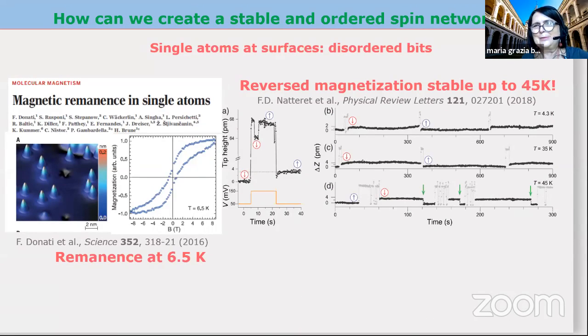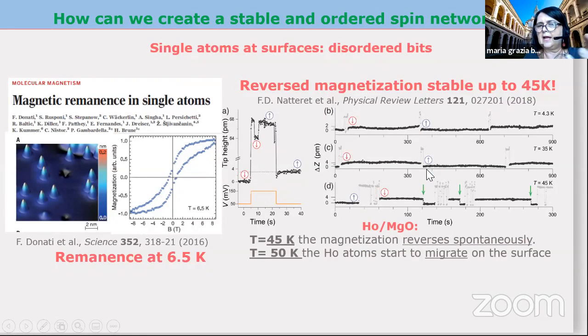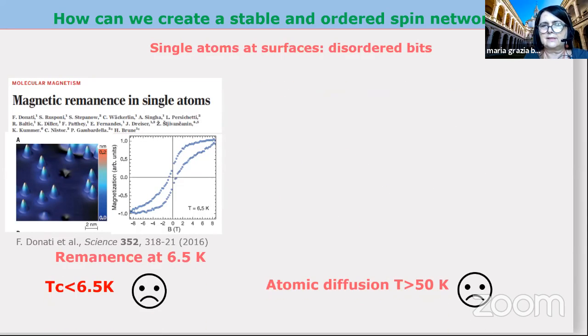Then there was another very interesting experiment a few years later on the same system. With a scanning tunneling microscope, they put a magnetic tip on top of the atoms, and they were able to reverse the magnetic response. So this spin down becomes spin up because the magnetic tip is approaching, and so on. If the temperature is very low, this is possible. But if you increase the temperature to 45 Kelvin, you see that the magnetization reverses spontaneously. And then the holmium atoms start to migrate if you increase to 50 Kelvin. So it's not possible to freeze the spin configuration on the surface. The remanence is only at 6.5 Kelvin, and the atomic diffusion destroys your magnetic states.